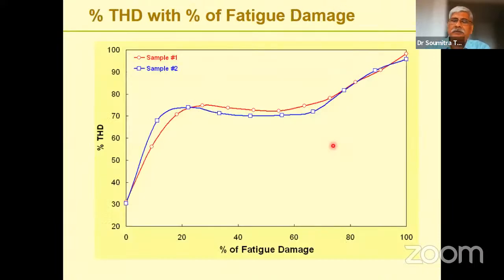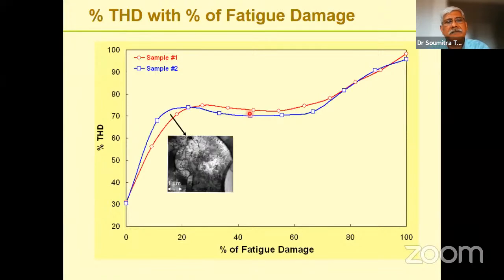So this is the type of correlation that we obtain between the total harmonic distortion and the percentage of fatigue damage. Percentage of fatigue damage given as a fraction of the fatigue life. And we find that replicate tests match very elegantly. And we find that there is a region, if you are within this, perhaps you can say that you have less than 50% damage and perhaps it is safe.